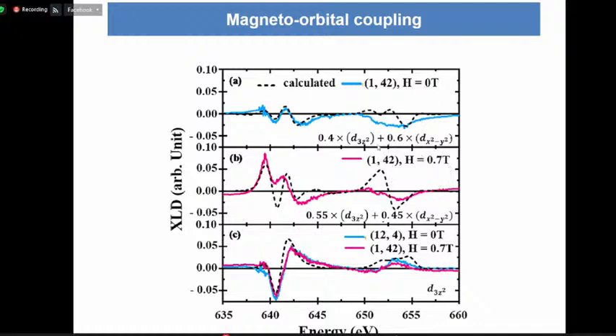Without magnetic field, this orbital is along the z direction. This orbital has 40% occupation, and the in-plane orbital has 60% occupation. But if we apply a magnetic field of around 0.7 Tesla, then the in-plane occupation is 45%, and the out-of-plane orbital is 55%. The percentage is changed because of the magnetic field. So the orbital can be changed by a magnetic field. This result showed that.